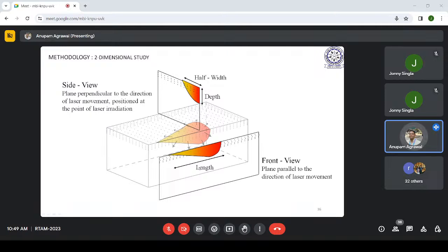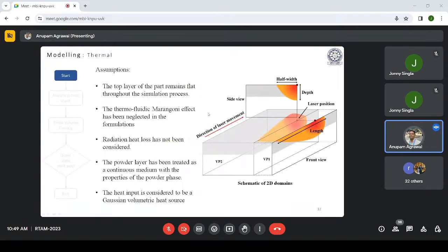In any analytical model there are so many assumptions. A few of the assumptions are listed. The top layer of the part remains flat throughout the simulation process, which means there is no unevenness in the powder spread. Initially the Marangoni effect was neglected in this analysis, and later results also include the Marangoni effect. The radiation loss has not been considered, as I mentioned earlier. The powder layer has been treated as a continuous medium with properties of the powder phase. So while making the computational layer, we have made it as a solid, but the properties given are powder phase properties. And the heat input has been considered as a Gaussian volumetric heat source.